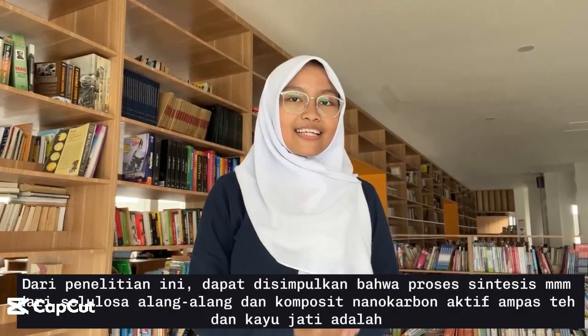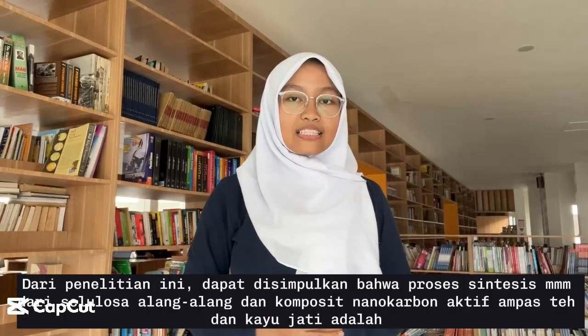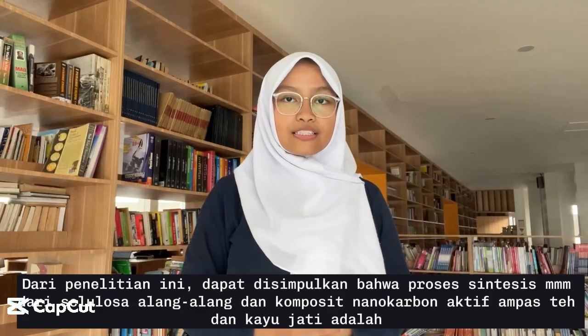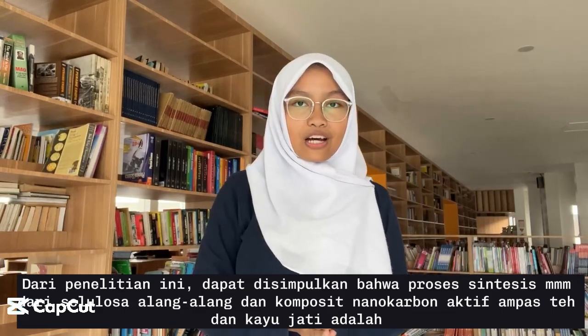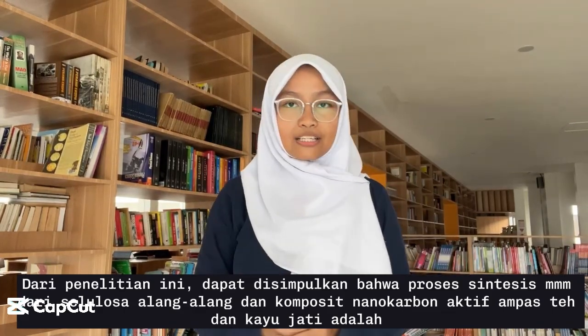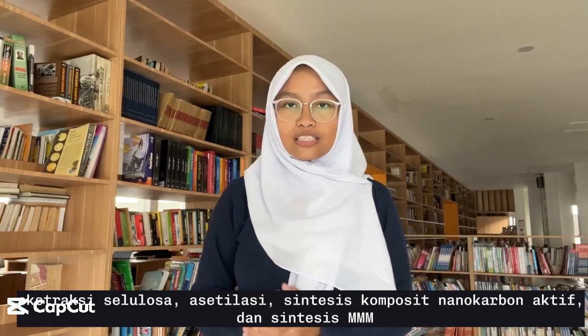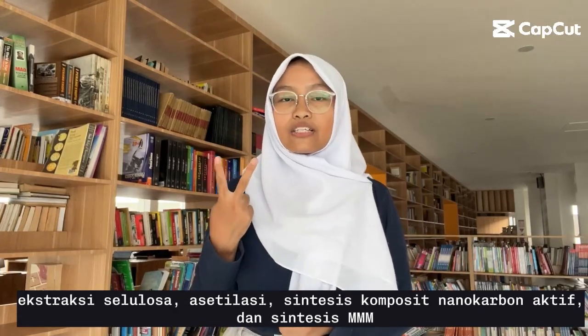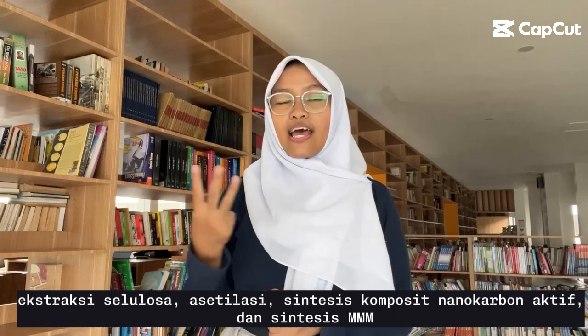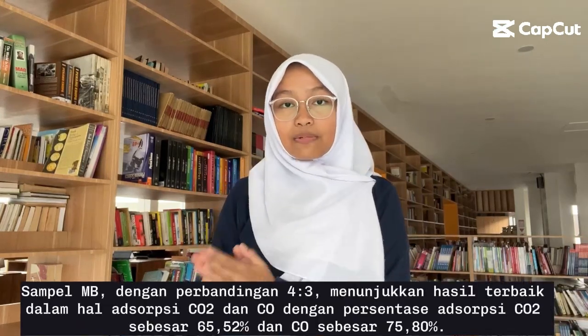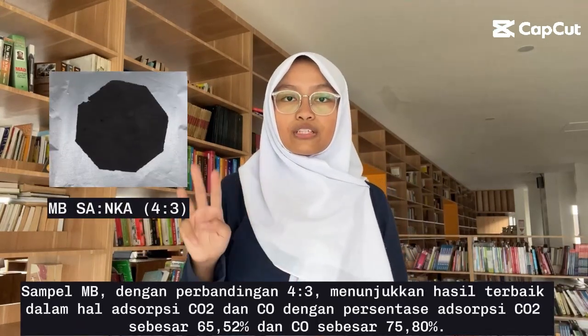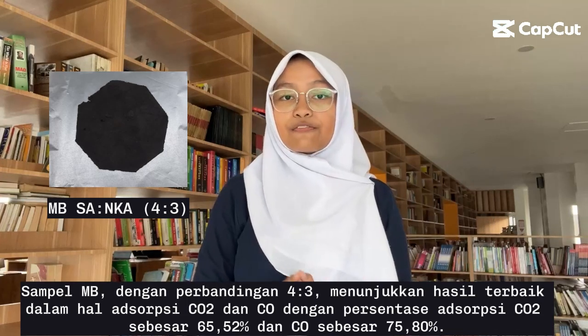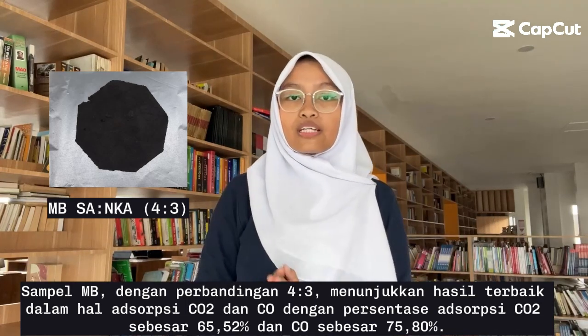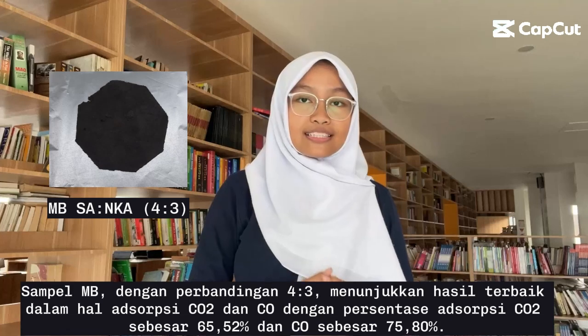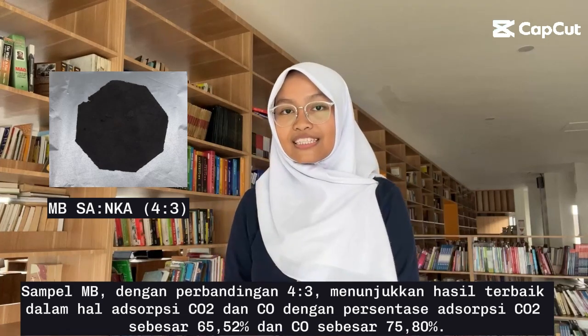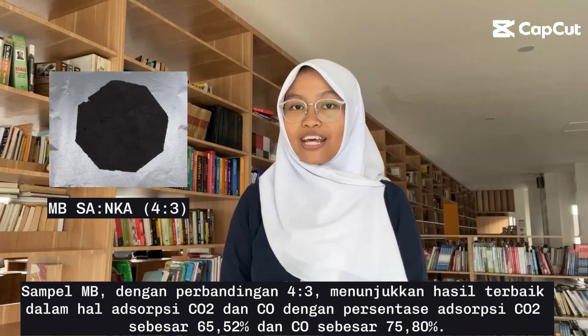So, from this study, it can be concluded that the synthesis process of MMM from alang-alang grass cellulose acetate and nano-activated carbon composite of tea waste and teak wood is cellulose extraction, acetylation, nano-activated carbon composite synthesis, and MMM synthesis. Sample MB with a ratio of 4:3 showed the best results in terms of CO2 and CO absorption, with a CO2 absorption percentage of 65.52% and CO of 75.80%.